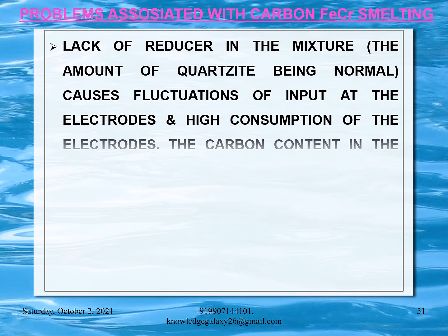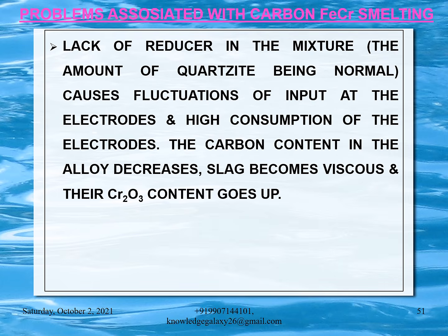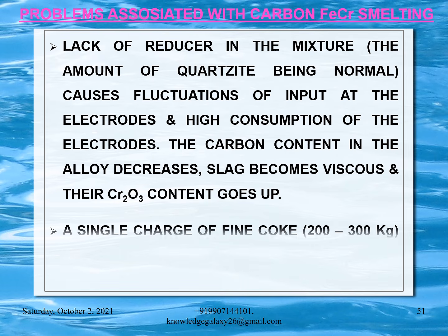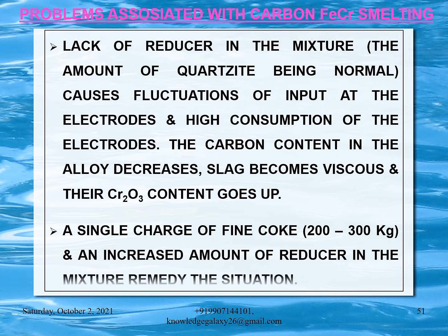Lack of reducer in the mixture, the amount of quartzite being normal, causes fluctuations of input at the electrodes and high consumption of the electrodes. The carbon content in the alloy decreases, slag becomes viscous and their Cr2O3 content goes up. This is one problem. So its solution is a single charge of fine coke 200 to 300 kg and an increased amount of reducer in the mixture remedy the situation. Let us now discuss the next problem.